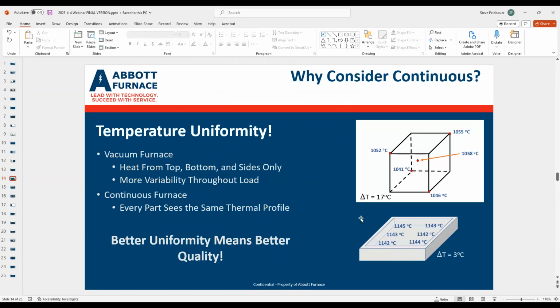The other reason that you want to consider looking at a continuous system is uniformity. In a batch system, it doesn't matter what type of batch system you have, you're always heating from the outside to the center, right? So the part that's in the center of the load is not going to see the same thermal history nor the same atmosphere flow as the parts on the edges, especially those parts that are in corners. I've heard many people talk about having difficulty even running parts in the corners of a load and getting uniform properties and performance compared to the center. And we've actually seen measurements with a delta T as high as 17 degrees C from corner to center on a batch system.